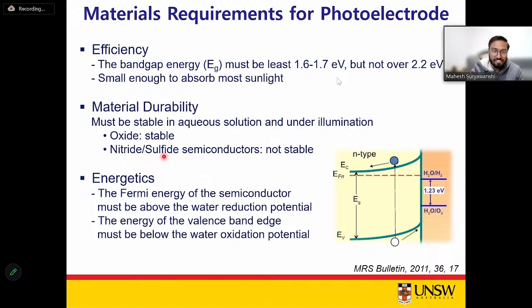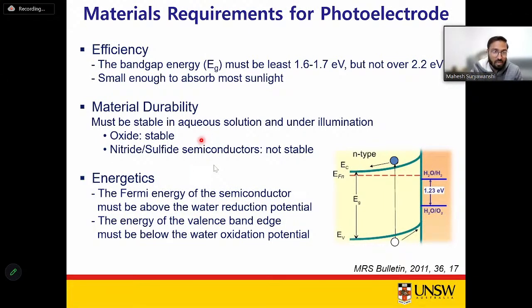So what are the materials that are capable enough to initiate this water splitting reaction? Of course, there are several oxides. Also, there are several nitride and sulfide semiconductors, which can be used as a photocathode or a photoanode for water splitting reactions. But only the oxides are quite stable in the electrolytes. However, you will not find any oxide photocathode or photoanode which has a band gap energy of about 1.6 or 1.7 electron volts. On the other side, we have several nitride and sulfide semiconductors in the band gap range of this one, but they are not stable in these aqueous conditions.